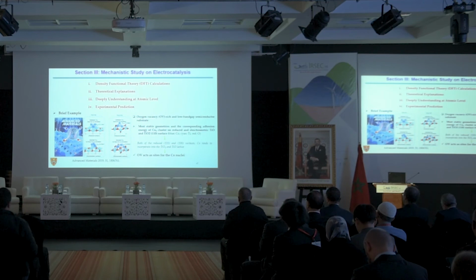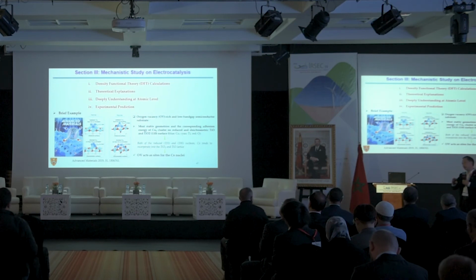So when we design the catalyst, before it was focusing on the materials itself. But at the same time, now we try to understand how these active sites really work during the cycling, during charge-discharge, during ORR or OER. So we try to combine with models like DFT calculation. Like this one, we calculated the oxygen vacancy, how this oxygen vacancy will affect the activity.